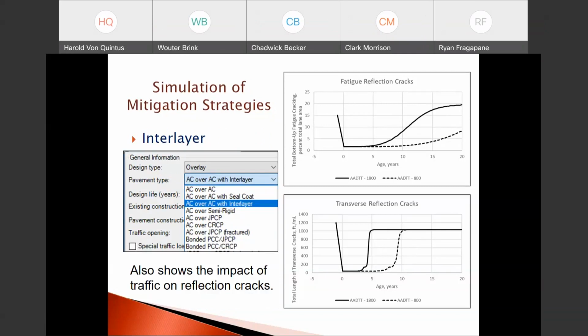So the top graph shows the same thing for bottom-up fatigue reflective cracks. The graph on the bottom shows transverse reflection cracks. The solid line for both cases is truck traffic of 1,800 per day. The short dash line is 800 trucks per day. So again, trucks are important, as well as the asphalt overlay thickness, with and without seal coats, with and without the interlayers. For the interlayers, there's a little bit greater impact for reflection cracking mitigation, or let's say delay. That's not going to prevent the cracks, but it'll delay them a very short time period, more than for the seal coats, based on the calibration data that was used from LTPP.